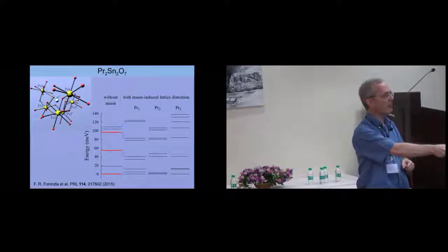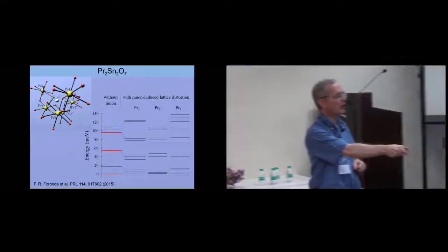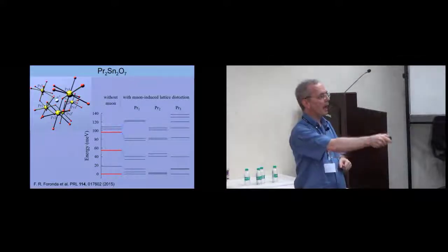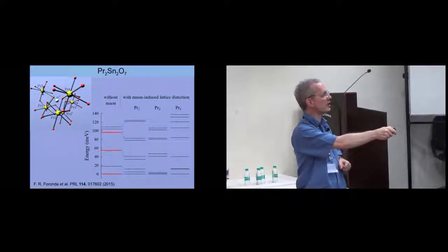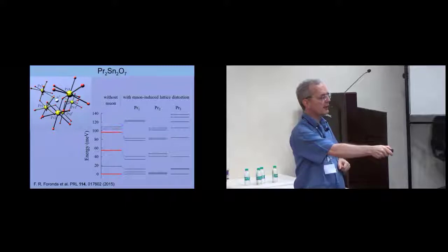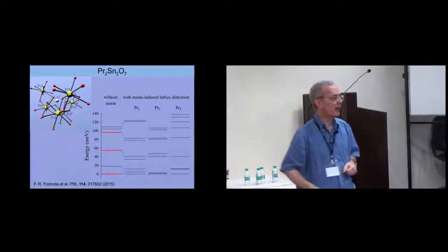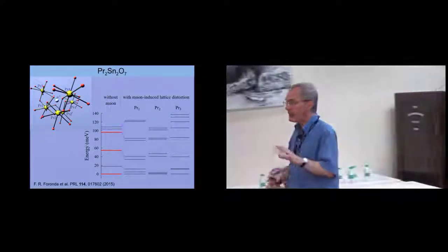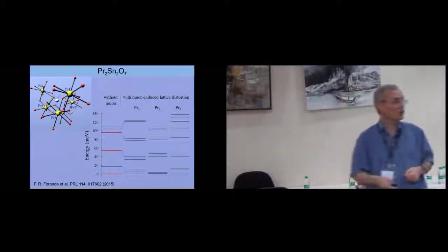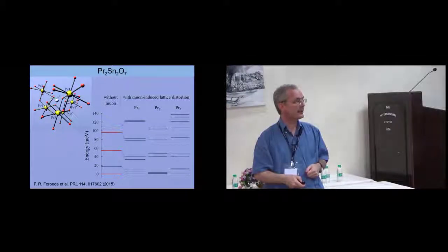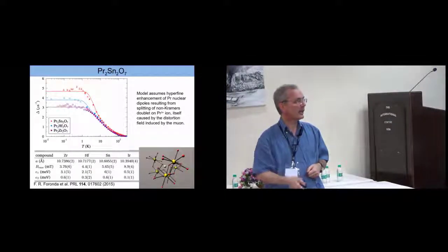So this is without the muon. The red here shows you doublets. And when you put the muon on for these different sites, 1, 2, and 3, which is this 1, 2, and 3, you can see that the ground state doublet splits by different amounts. And this splitting changes the local properties. And this turns out to be very important.